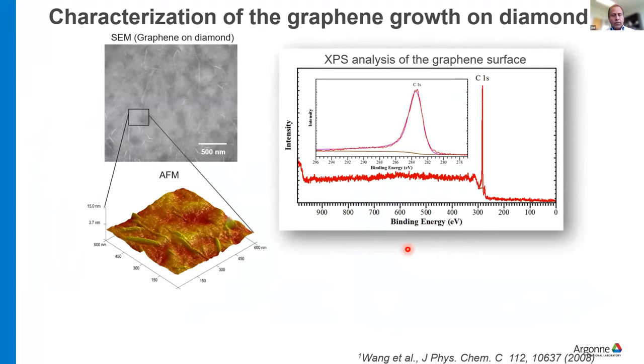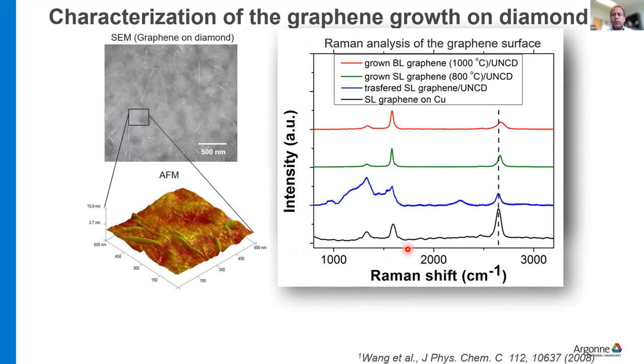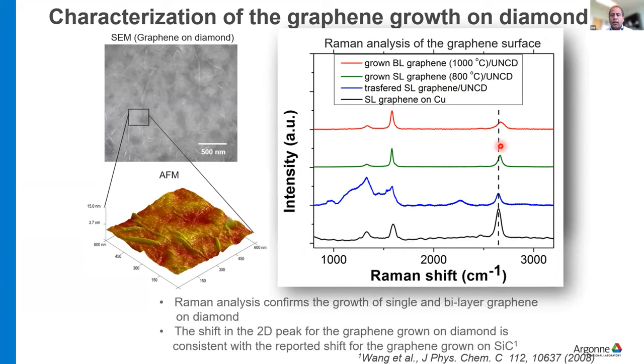If you see, there are some wrinkles on the graphene that might create some problems. But there were no traces of nickel, as you can see from the XPS, and also no oxygen at all, which basically shows very high quality graphene grown. When you compare the Raman spectra with the single layer graphene on copper or the transfer, you see there is some shift in the 2D spectra. And that is very typical of when you grow an epitaxial graphene on silicon carbide, because there's a bonding between the graphene and the underlying substrate that produces some strain. And then there is a little shift that you see in this 2D spectra. But we saw that very high quality graphene can be grown.